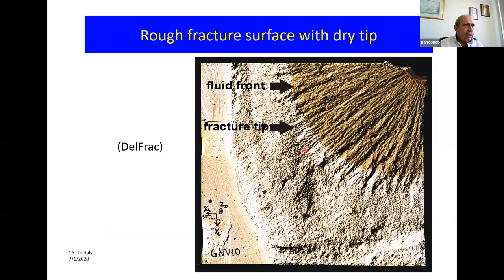So, and this is one of the pictures actually from the Delft consortium, which show the fracture roughness in the weak plaster. And you can see in this case, in the area where the fracture was propagated, in the wet area and in the dry area, the fluid front is here, the fracture tip here. You can see how rough is the surface, probably due to plasticity.